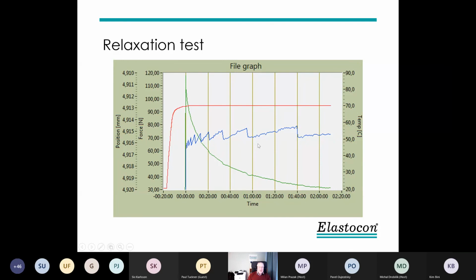We can see that on this graph. Here we are doing a relaxation test. The red is the temperature, 70 Celsius. The blue is the position. Why does the position look like this? Because we have quite a quick reduction in force to start with. And in this case, the servo motor will compensate for every 1/1,000 millimeter. So all the steps here are 1/1,000. If you look out here, there is 1/1,000 between these 2 steps. So we can measure with 1/10,000. And the correction gets less and less when we continue the test.